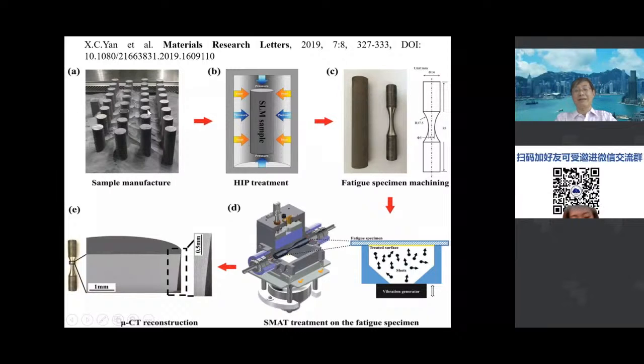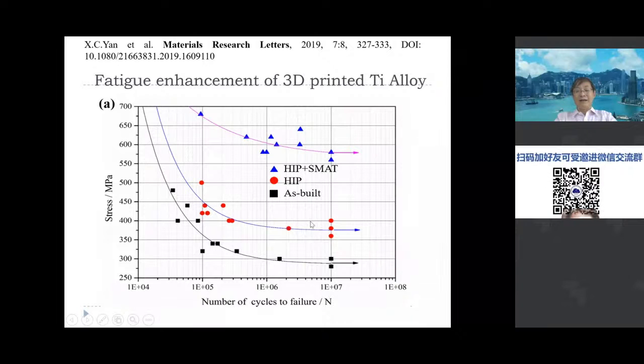For this reason, we made a 3D printed large sample according to the ASTM standard and then treated it using SMAT. And as you may see here, the as-built 3D printing structure can only have a fatigue strength of 280. With HIP, you can only enhance a little, but with HIP plus SMAT, you can roughly double the fatigue strength of titanium alloy.